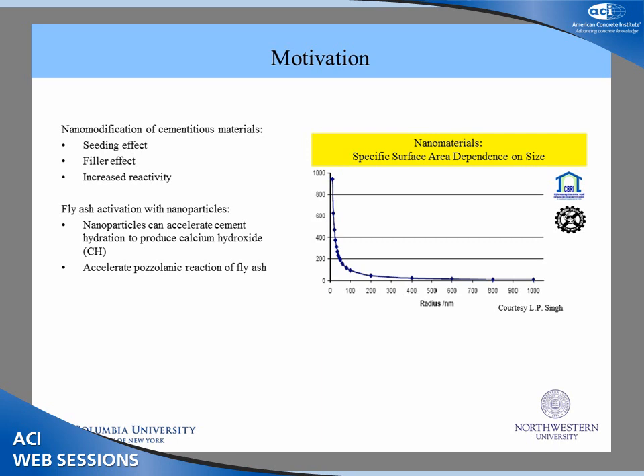So our rationale was, why not cater this technology towards activating fly ash? Because through the use of nanoparticles can accelerate cement hydration, and this will lead to the production of calcium hydroxide. Fly ash, as a pozzolanic material, consumes CH to produce secondary CSH. So by activating fly ash through nanoparticles, we can accelerate the pozzolanic reaction of fly ash.